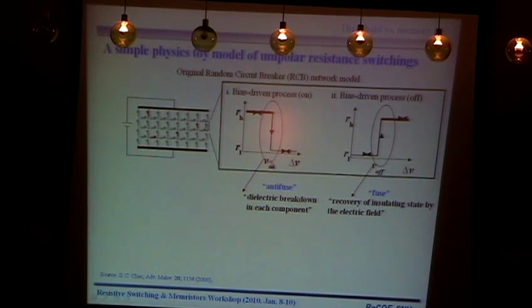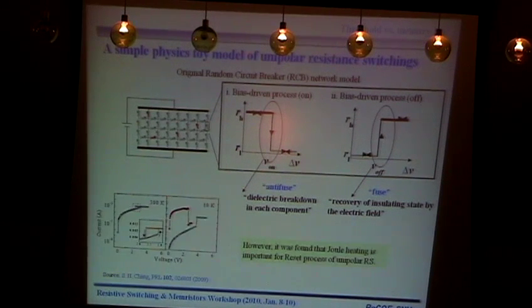There is some kind of voltage where this high resistance circuit breaker will switch to the low resistance state. This is called anti-fuse, and it is very similar to the dielectric breakdown in each component. On the other hand, at V-off, the low resistance state will change to the high resistance state, and this is called a fuse, or a recovery of the insulating state by the electric field.